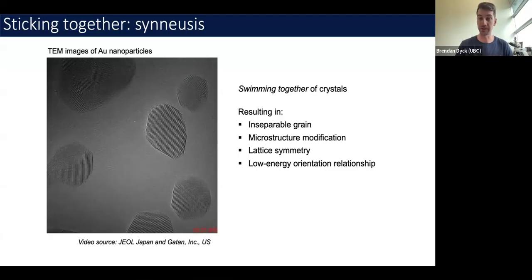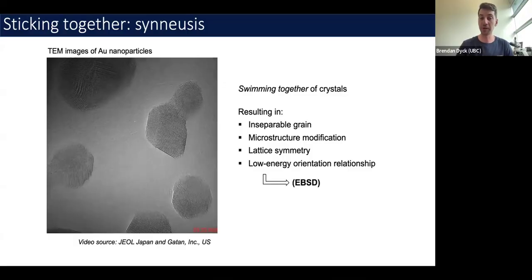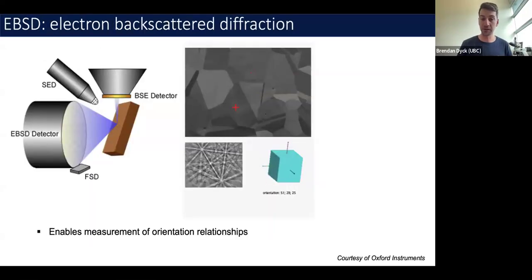And the lowest energy orientation relationship is where we have the most coherency across those two crystalline lattices, right? So it can be lower when we have the same minerals coming together. It would be higher if we had two different phases, but even in that situation, there's going to be a lower and a higher energy configuration. And why that's really important is because as soon as we get into orientations, it opens up the ability for us to use a technique like electron backscatter diffraction, which allows us to actually image crystal orientations to look for these patterns in nature. So I'm going to show you an example of that, but first I want to just explain how this technique works if you aren't familiar with it.